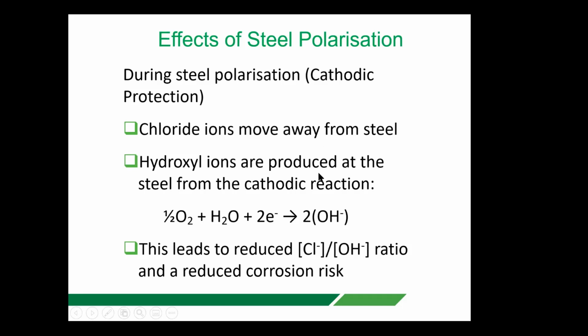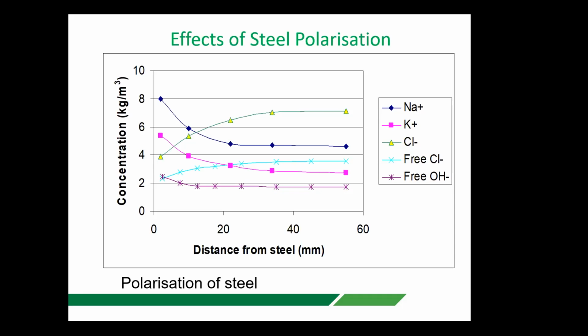And that total result is that you are continuously reducing the chloride to hydroxide ratio, and therefore the corrosion risk of the steel reinforcement. There is actually a critical chloride to hydroxide ratio below which there's no more corrosion. So the attempt really is to try and reduce the chloride to hydroxide ratio fairly early on in the application of cathodic protection to be able then to switch over to cathodic prevention. And we've seen that in the lab when we looked at ionic concentrations when we applied current.